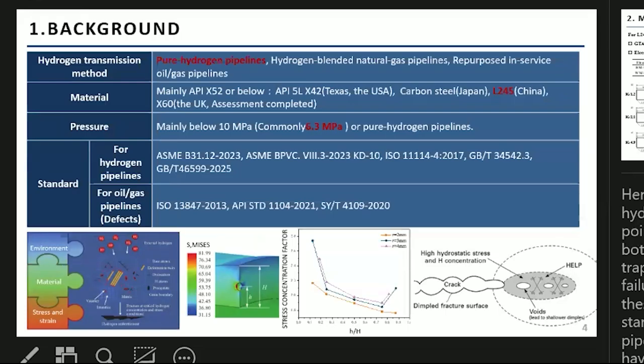The key point is that a welding defect acts as both a stress riser and a hydrogen trap, making it a critical zone for failure. But current assessment of these defects still largely relies on standards developed for oil and gas pipelines. To address this gap, we have conducted experiments based on the condition highlighted in red here.